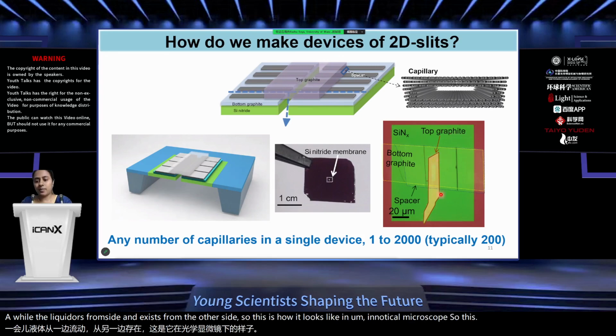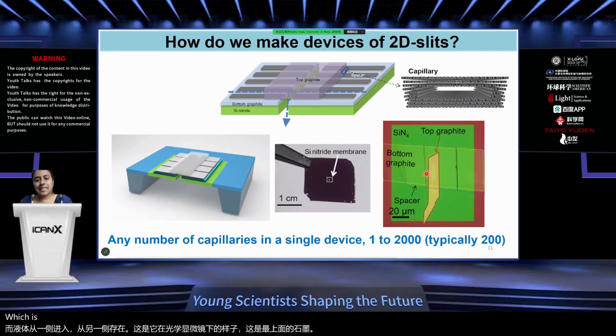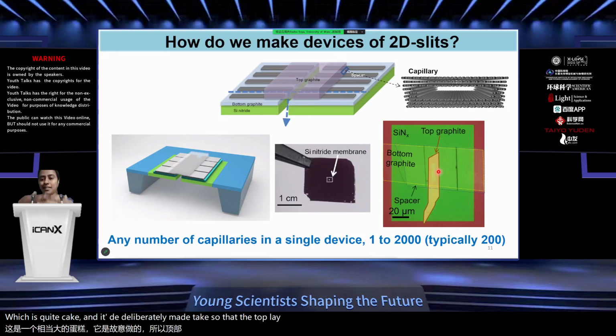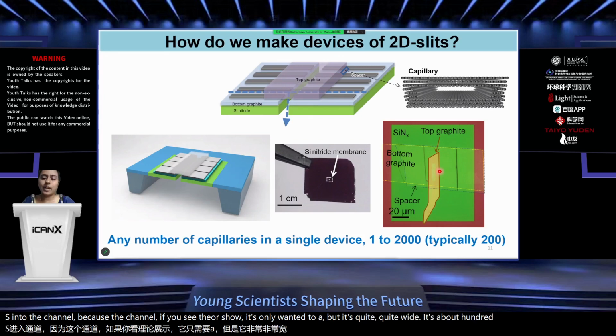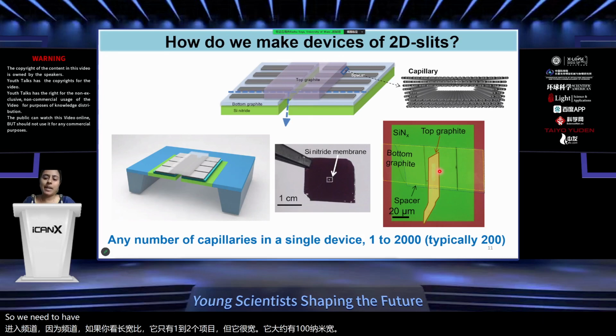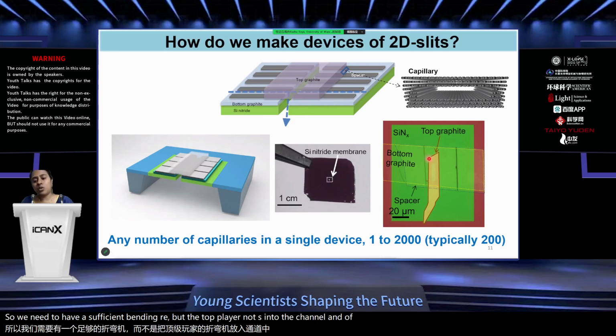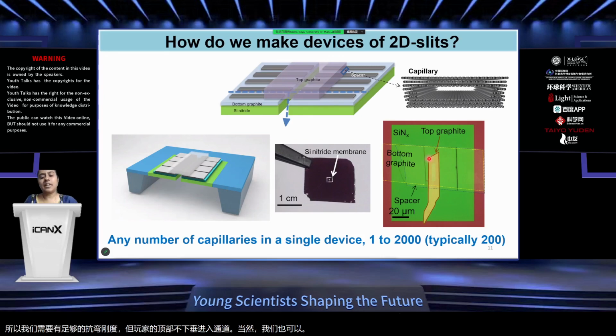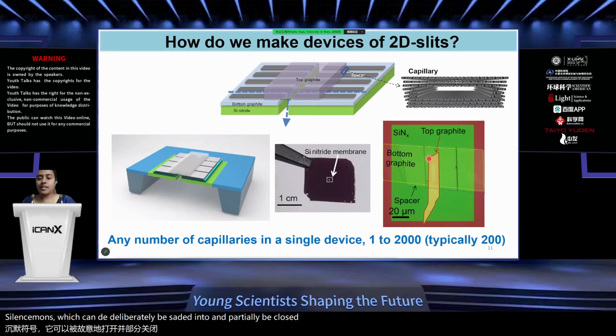So this is the top graphite, which is quite thick, and it's deliberately made thick so that the top layer doesn't sag into the channel, because the channel, if you see the aspect ratio, it's only 1 to 2 atoms thin, but it's quite wide. It's about 100 nanometers wide. So we need to have sufficient bending rigidity for the top layer not to sag into the channel. And of course, we can also make channels which can deliberately be sagged into and partially be closed for specific experiments. So we also do that. So that is also possible.